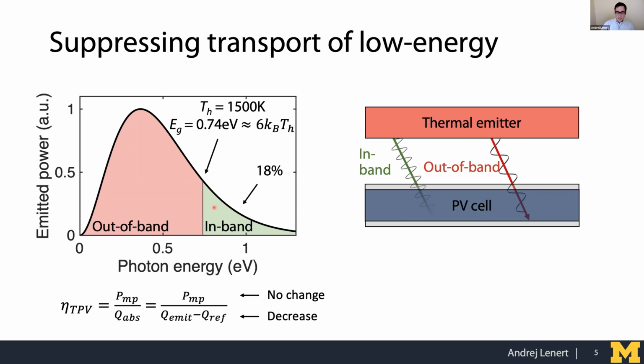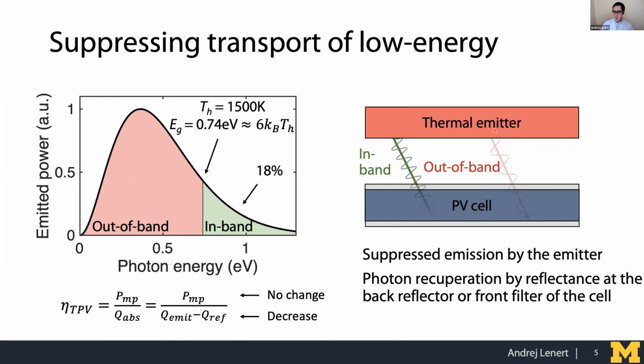But what we're left with is we have to manage a large amount of radiated power that's out of band, that's at energies below the band gap. Usually this accounts for 75 to 80% of the overall radiated power. So the approaches to suppress out-of-band radiation or radiative heat transfer can be categorized as either emission suppression, so emitters that use structures or filters to suppress emission, or another approach is to reflect that low energy radiation selectively back to the emitter.